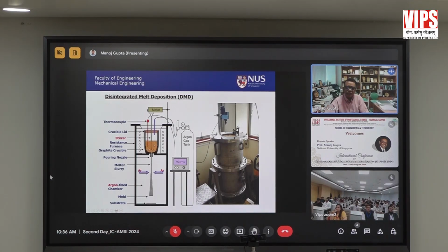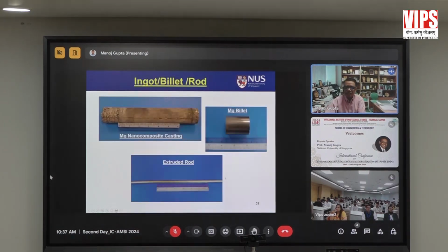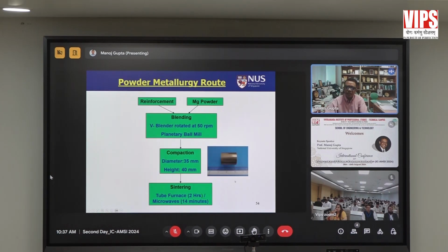Here we take the material in a graphite crucible. We use resistance heating to heat it. We stir the material, which can be a monolithic material or a composite material. We bottom pour it, and once we are pouring, we hit it with argon gas jets so that it is split into droplets, and then we collect it at the base of the chamber. What you see on the right hand side is the typical facility that we have in the lab, working very well for the last 30 years now. These are the ingots you can get, which you can machine into billets and rods.